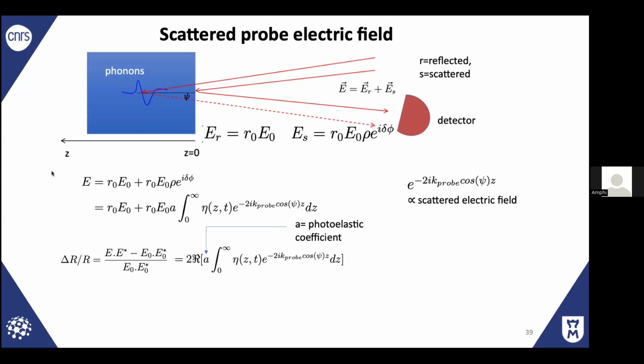This is the electric field. And there is a scattered one, which is proportional to the incident, and it is modulated by rho, which is smaller than 1, of course. And this is a change of phase as well. And that change in intensity and phase is related to what? Just to the convolution between the scattered electromagnetic field, this is the transfer momentum of the light, and the strain, for the acoustic phonon point of view.